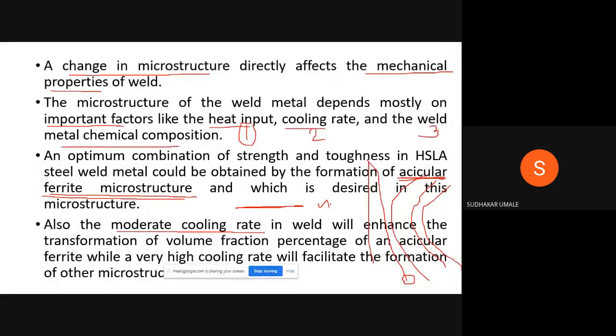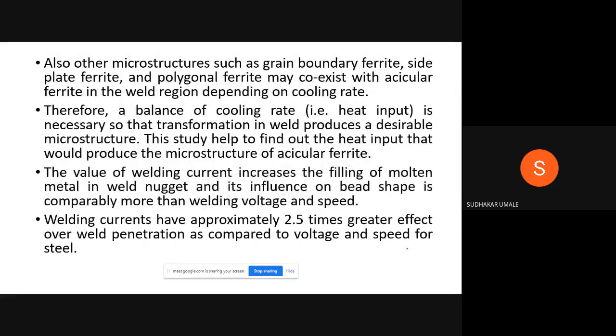I do not want martensite structure in the microstructure in the base metal, because the base weld pool becomes so hard, and I cannot do the machining later on. And hence I am trying to get the very suitable material which has higher ductility. I want very ductile material, and the ductile material comes because of acicular ferrite, and we will concentrate on these three. And then I will explain what the microstructures are.